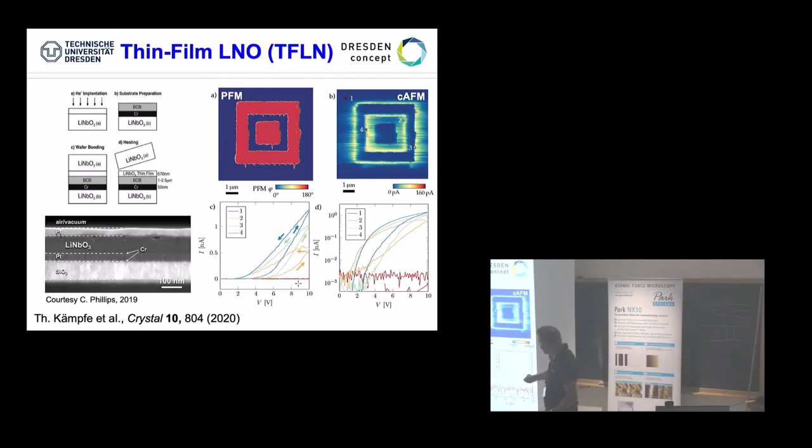In order to do so, we have here a very nice TEM picture from this sample. You see the thickness typically is on the order of about 100 to 200 nanometers. So, Thomas in my group did the following. He said, okay, why not write, as we always do, domains in this kind of thin film. So we're doing PFM measurements, writing domains, squares, and then measuring IV curves at different positions, 1, 2, 3, 4. So, again, up and down domains, as we know from the macroscopic view, and then measuring the currents, and you see, nicely, there are currents going up and going down.